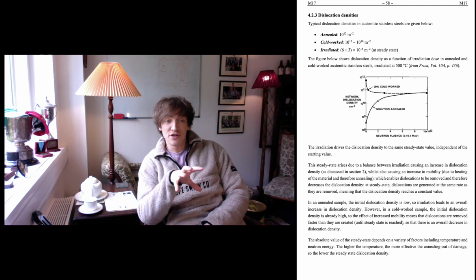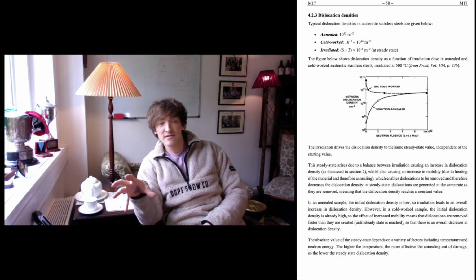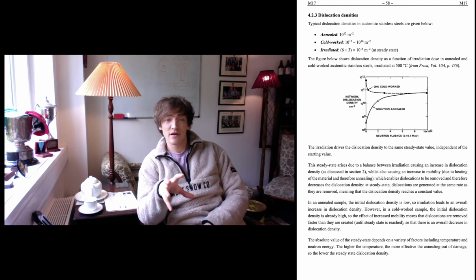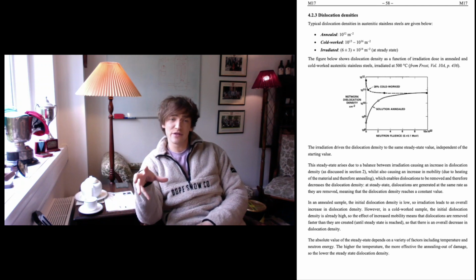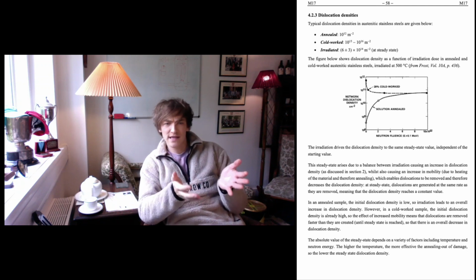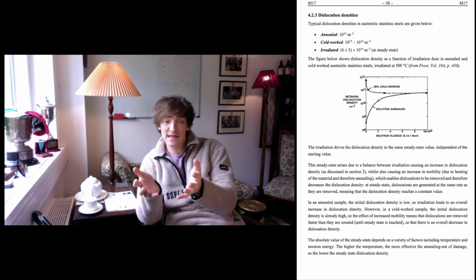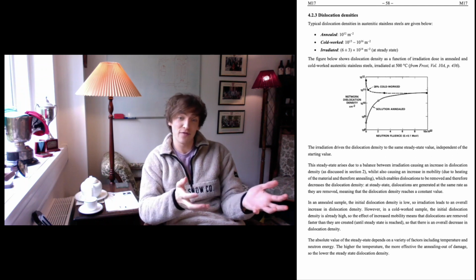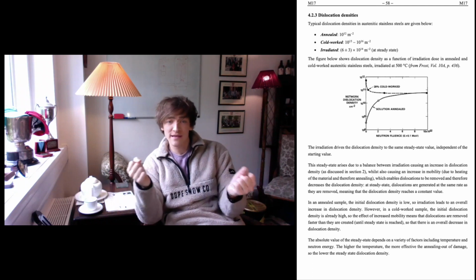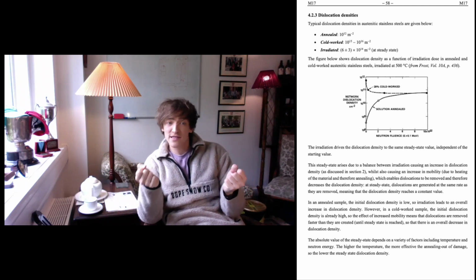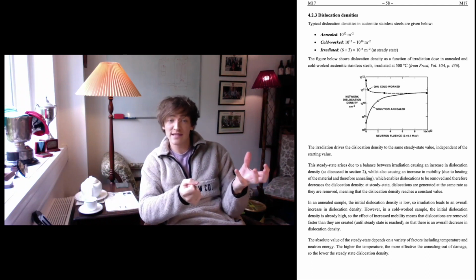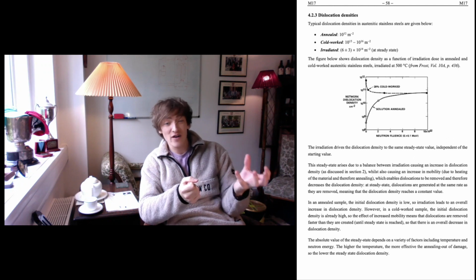Cold worked reduces the dislocation density in number. Solution annealed sees an increase in the number of dislocations. And that occurs because there is a balance between irradiation causing an increase in dislocation density, but also causing an increase in mobility, which allows dislocations to be removed. So those two processes are battling each other. And in cold work samples, the increased mobility means the dislocations are removed a lot faster than they are created.